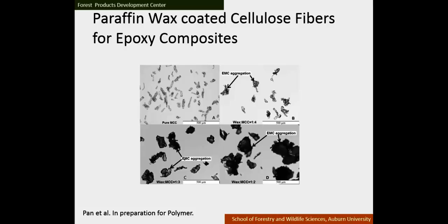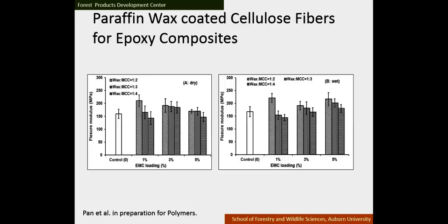And so what we did was we simply created different ratios of wax to microcrystalline cellulose. And you see as you go from pure cellulose on the top left to right, you can see more and more wax being put on. Of course, the whole idea of putting cellulose in a composite is to increase the strength. So if you start putting wax around it, then you've got a balancing act, because now the cellulose can't react with the polymer that you're putting in it.